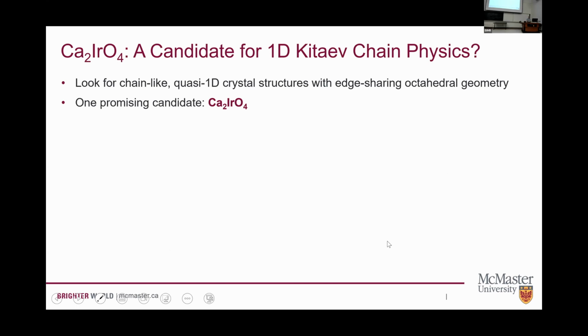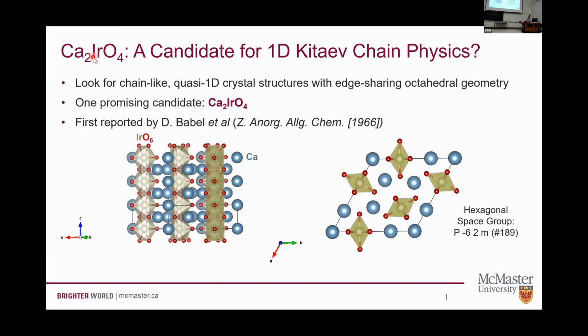So we decided to look for low dimensional iridium-based materials. And the place that we decided to start was calcium iridium oxide. So this 214, sort of a surprising low dimensional material. This is the same kind of stoichiometry as the layered perovskite iridates that seem to be analogous to high TC superconductors. But this calcium 214 was first reported in the 1960s.